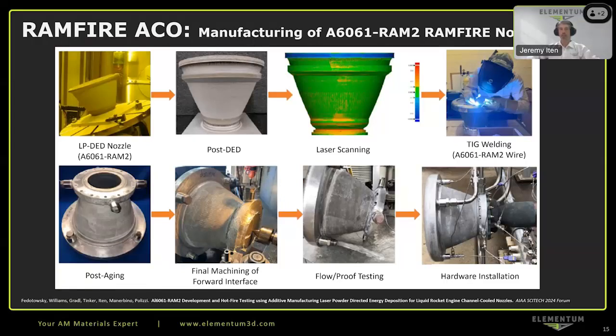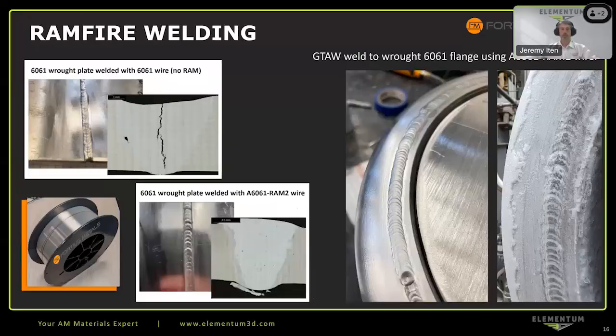And then this was an opportunity to demonstrate the ability to join a traditional legacy wrought 6061 component to the printed RAM2 component and use the high strength 6061 RAM2 wire to do that to get a weld strength that otherwise would have been unachievable. There's the part in the bottom left after the heat treatment process. And then there was some machining of the manifold and the nozzle at the joint in the weld. So there was then subsequent flow and proof testing of the component, followed by the hardware installation, and then the hot firing, which I'll get into later.